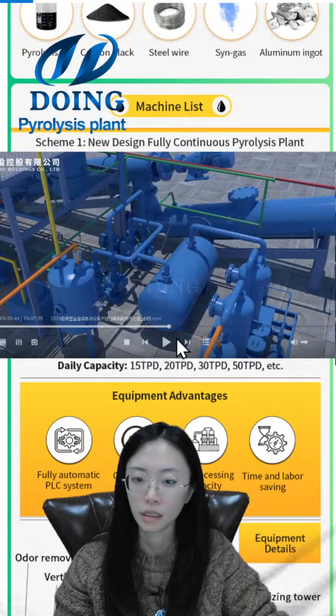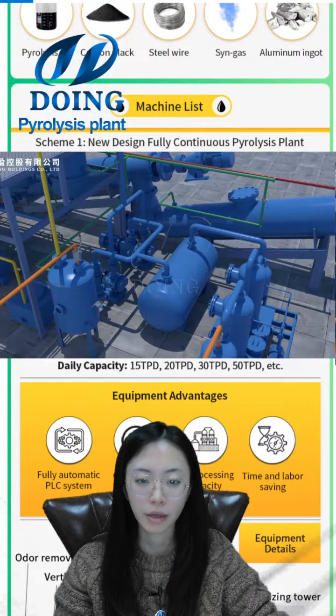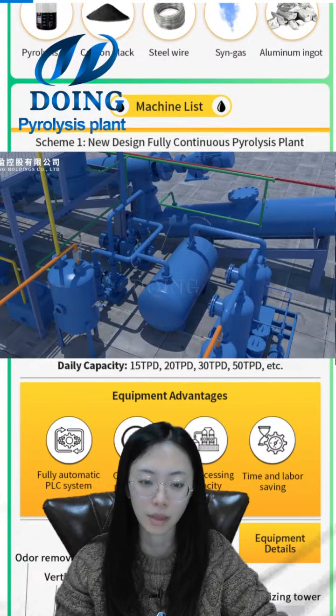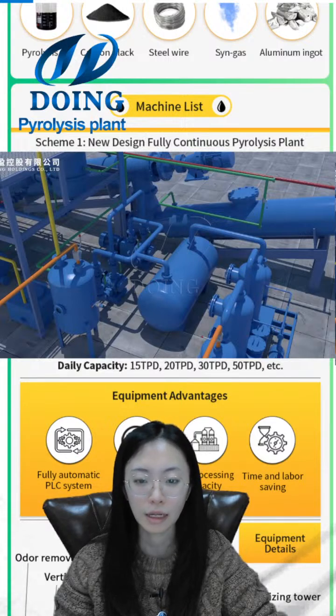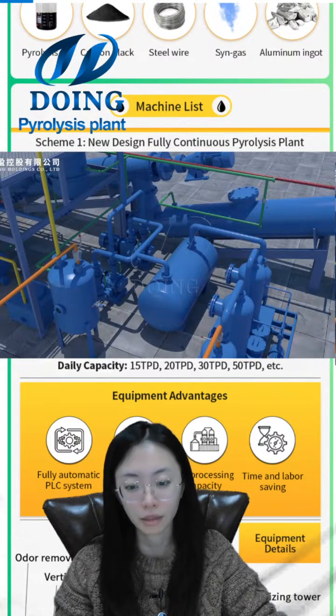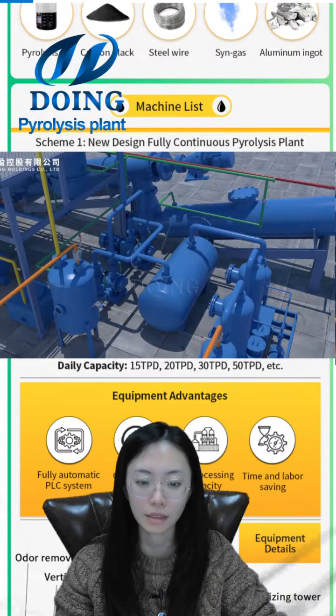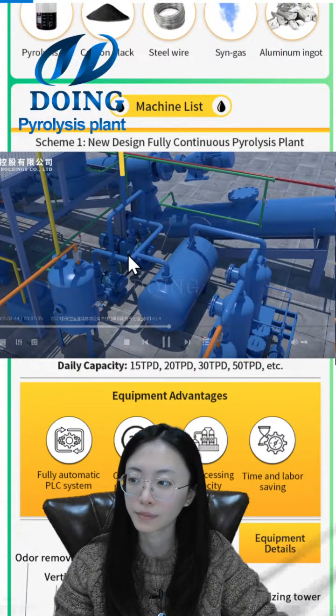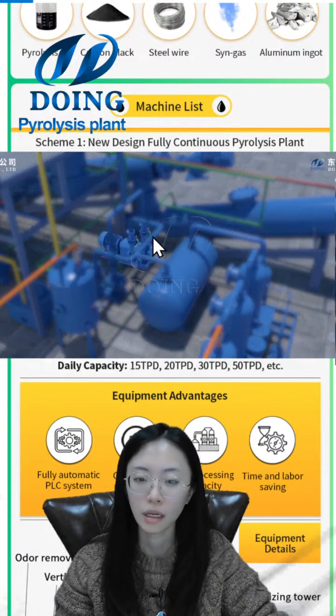This is the new design. We use the micro-negative pressure process to reduce the contact between the carbon black and the oil gas. That can reduce the residual oil rate of the carbon black and improve the light transmittance of the toluene, and that allows further processing of the carbon black to high quality and enhances the value of the products. This is the negative pressure device.